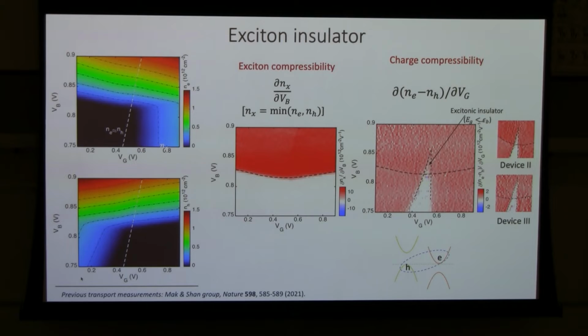And similar behavior was actually first reported by an electrical transport method by the Cornell group. The explanation is basically that at this bias voltage, the conduction band and the valence band are getting very, very close to each other, but still not overlapping. So in that case, you cannot inject electrons and holes in the system, but it's possible to inject a combined exciton in the system because excitons have lower energy compared with individual electrons and holes.